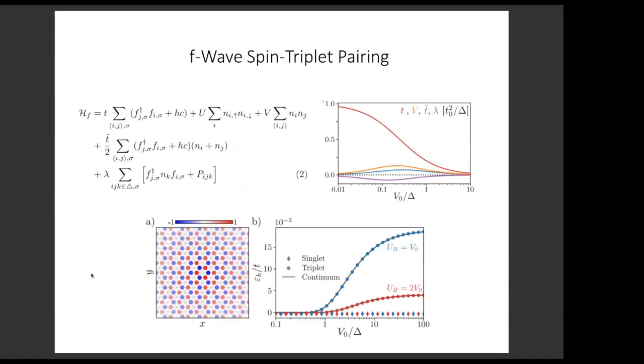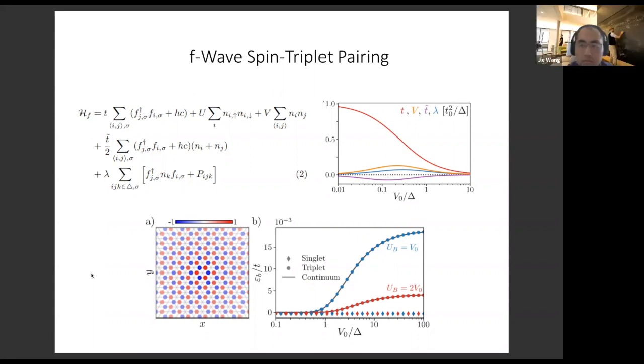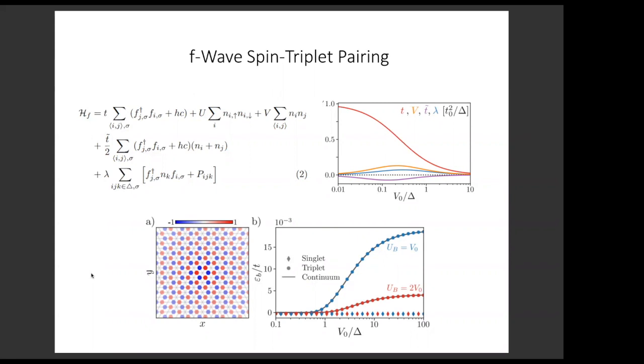I won't go through all the derivations again, just to show the same kind of Schrieffer-Wolff transformation. We can eliminate the high energy processes and derive an effective Hamiltonian for the doped electrons. The form of the effective Hamiltonian is very similar. There's now an on-site energy U because of the local repulsion. There's a correlated hopping just like before. There's also another correlated hopping between just two sites, which turned out to be not important at all. So what we found, just by solving the two-particle problem, is that you see an F-wave bound state in a large parameter range.